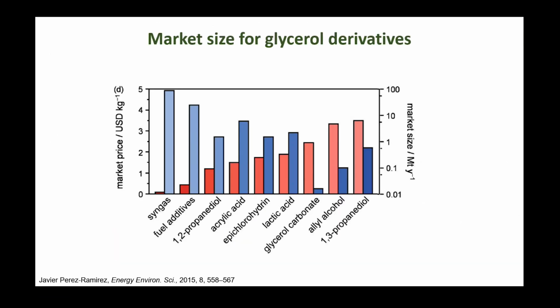So then we took a step back from this mechanistic study and we went more with the chemical engineering hat on and thought, what do we want from this process? Because clearly making all this mixture of organic acids in water via glycerol oxidation is not such a good value in terms of technoeconomics, because the hydrogen that you produce, you will never get to the same scale as with water electrolysis.